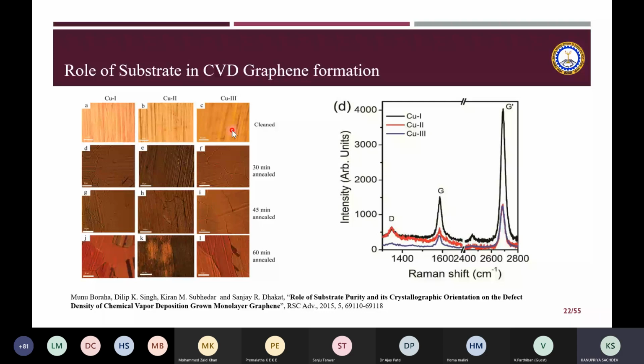In this case, the authors have taken 3 substrates, where you can see that the microstructure is different. When the graphene was grown on these 3 substrates, which they have named copper 1, copper 2, and copper 3, you can see that the graphene growth is very much affected by the substrate smoothness. The intensity of the peaks is very different in all the 3 cases. This spectrum is a Raman spectrum of graphene, which is like a fingerprint method to identify graphene. You can see that there are 3 peaks in this spectrum, D, G, and G dash, and we'll have a look at what they actually mean.